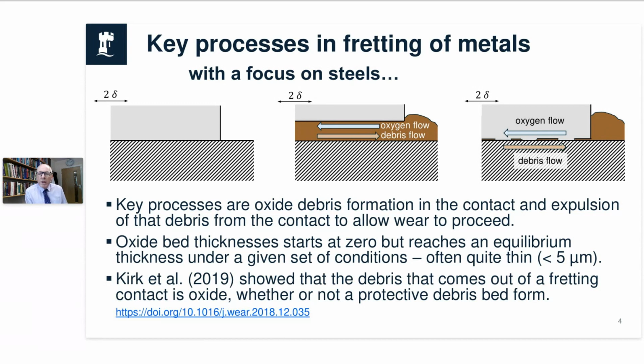Sometimes the oxide is like that. Sometimes the oxide is much thinner, patchy, you might describe it as. The right-hand side of my 3 images there. And we can still then be getting oxygen flow in and debris flow out, but it might mean that either the debris is flowing out really rather quickly, it's very easy for the debris to flow out, or it might mean that the oxygen is struggling to get into the contact. It's difficult to distinguish when you see a thin or patchy oxide with lots of metal in the contact. It's difficult to quite know what the difference is, but it at least provides us with some level of understanding through our framework.